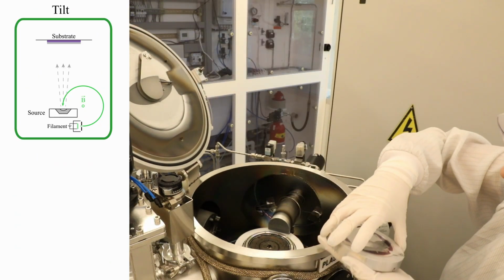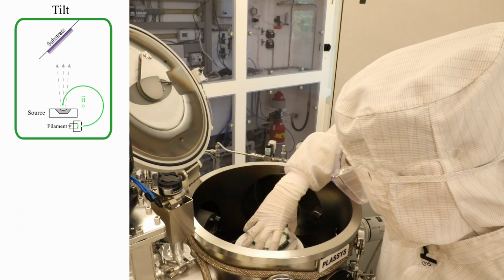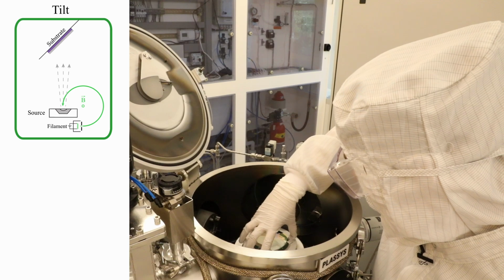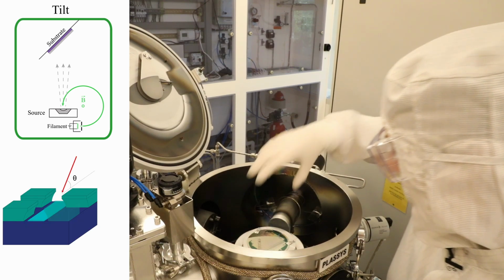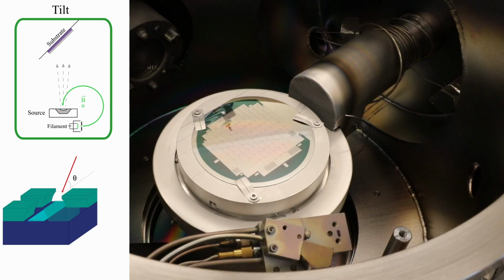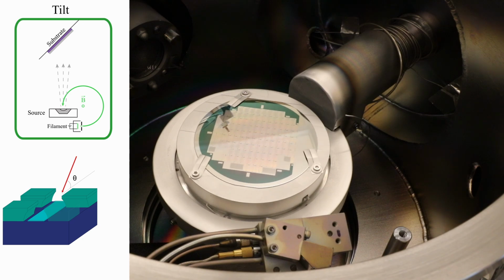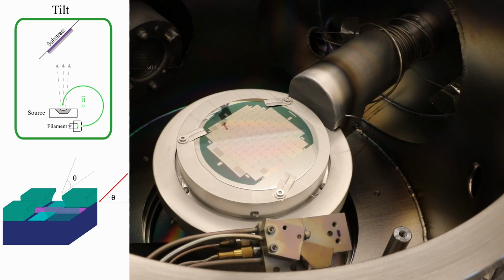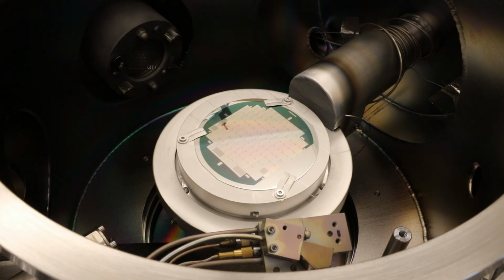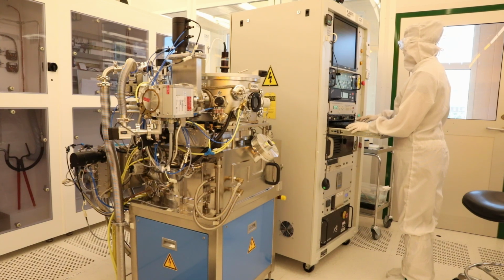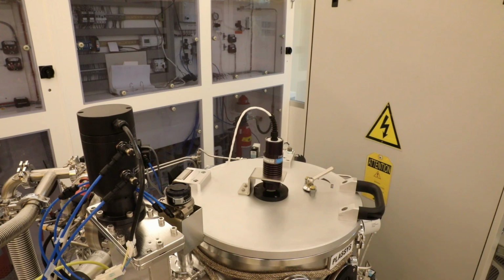This time, to also make the shadow evaporation work, we will tilt the substrate 45 degrees with regards to the source. We will also rotate the wafer in between the 3 consecutive depositions to guide the evaporated aluminium into the current resist trench of choice. Unfortunately, evaporation is not as spectacular to witness as sputtering, so I don't have much to show you here. So I'll skip ahead to when I have completed all 3 consecutive depositions and am ready to unload the wafer.